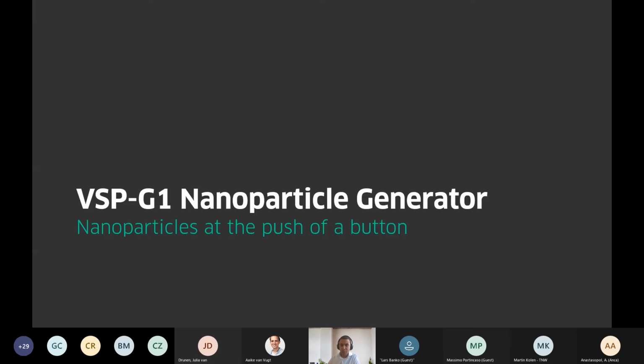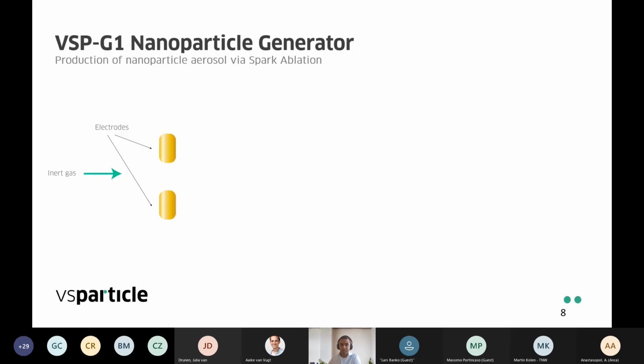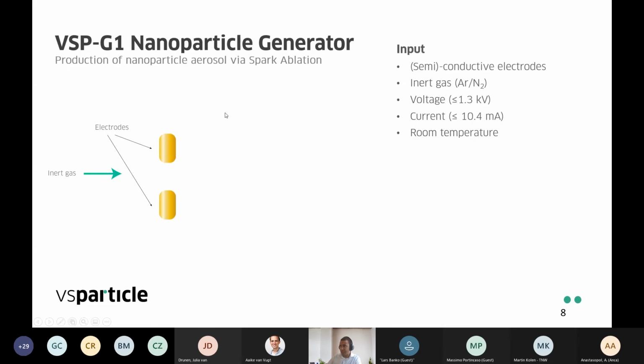First, the G1 Nanoparticle Generator. So our VSP-G1 Nanoparticle Generator uses spark ablation as the method to prepare its nanoparticles. So what I show you here are the ingredients that you need in order to be able to prepare these nanoparticles. To start with, you need to have conductive or semiconductive electrodes. You need an inert gas, so this can either be argon or nitrogen, which can then remove or take away the aerosol of nanoparticles that's produced. You need electricity, and the entire procedure runs at room temperature.